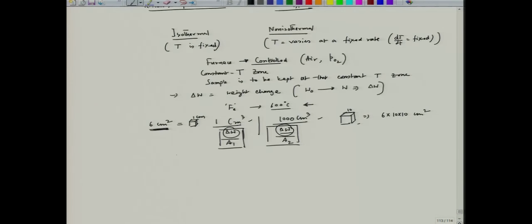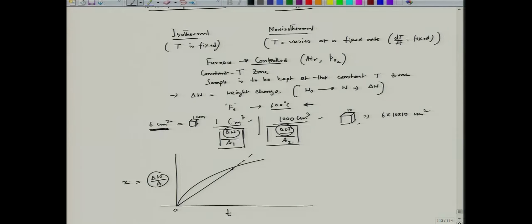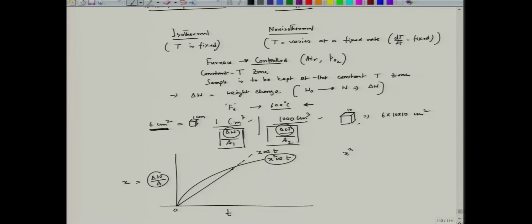And what do we plot? We plot del W by area as a function of time, and since this is the 0 point, it can be like this, it can be like this. If this parameter is considered to be x, then x could be proportional to t, x square proportional to t, or x cube, or it could be logarithmic. Our interest would be the parabolic one, because in many cases we see that a parabolic rate law is followed, except a few cases like zirconium, where we see that a cubic law is valid, where x cube is proportional to t.